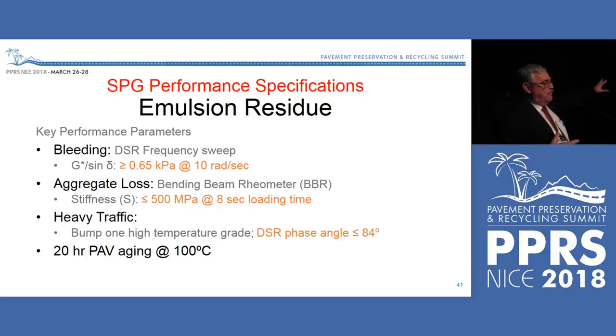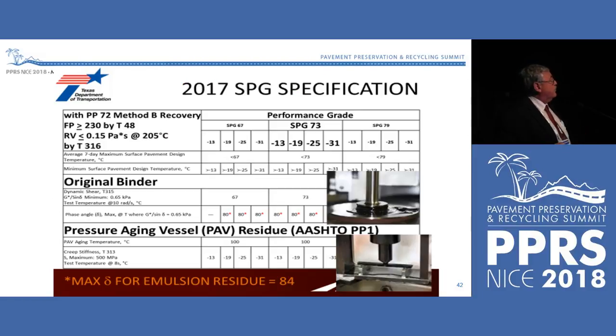So we have to decide among these options, as well as others being offered us, which might be the best failure criteria. Everybody's after the same failure. It's the test methods we have to judge which delivers the right answer. This procedure includes 20-hour PAV aging on the emulsion residue before we do the low temperature testing for aggregate loss, whereas the EPG system from North Carolina State did not. So more differences to work out. This is what the Texas spec looks like.